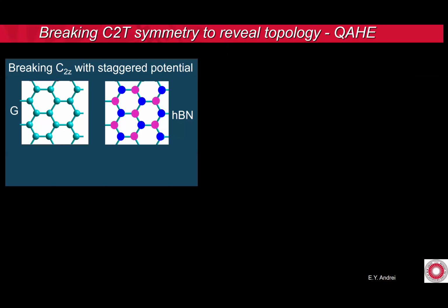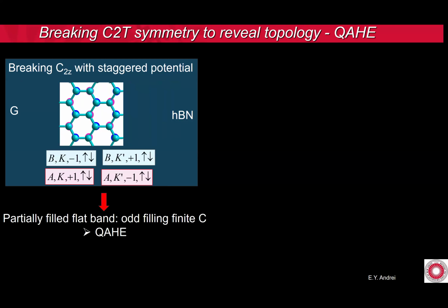Okay, so let's look at breaking inversion symmetry. So let's say that I have my graphene here. The A and B sublattices are populated by the same carbon atom. And I have boron nitride, which is a sister lattice, which looks pretty much like graphene, except that you have different atoms in the 2 sublattices, which gives rise to the large gap, the 6 eV gap. And now if you superpose the 2, you have broken the inversion symmetry because of the energetics: when you put a carbon atom on boron, it really likes to sit there. It has a lower energy than when you put it on nitrogen. And now we've broken the symmetry.